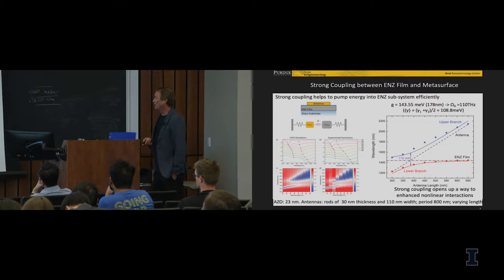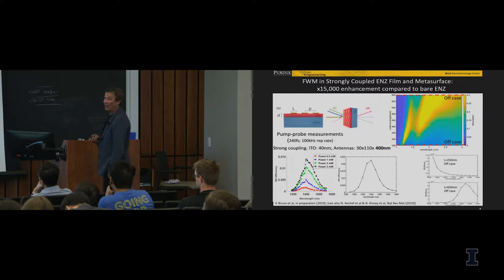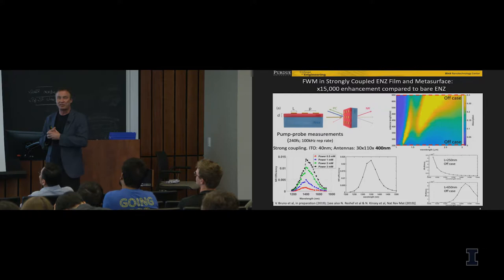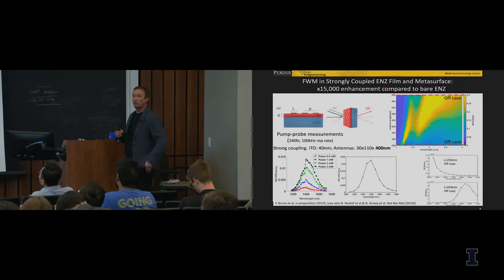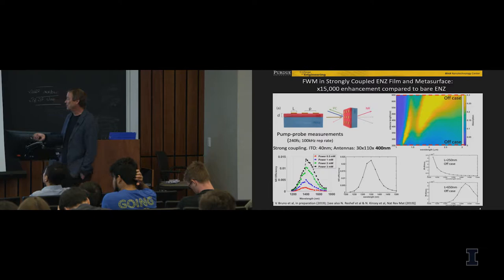So what we obtain as a result, by adding a metasurface on top of this ENZ substrate, you see enhancement of nonlinear response by 15,000. So on top of the enhancement provided by ENZ materials, because the linear refractive index is small, as I pointed out, but you have a problem with this impedance mismatch, in this case we have an additional enhancement of 15,000 because you very efficiently couple light energy inside of this ENZ material. And we have very good agreement between experiment and full FDTD nonlinear simulation.